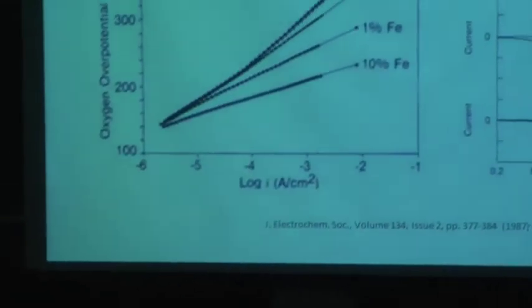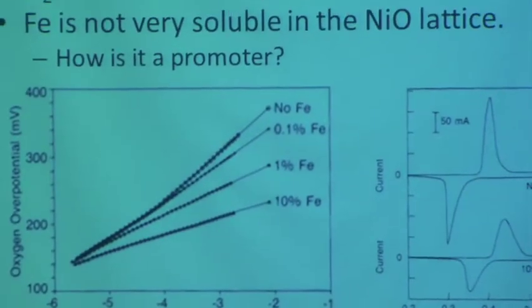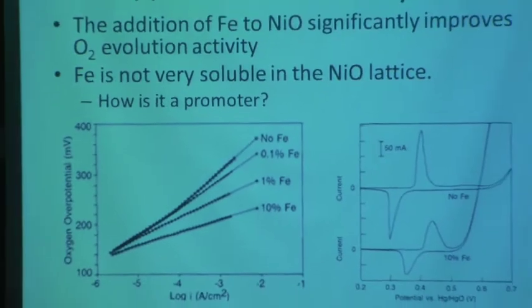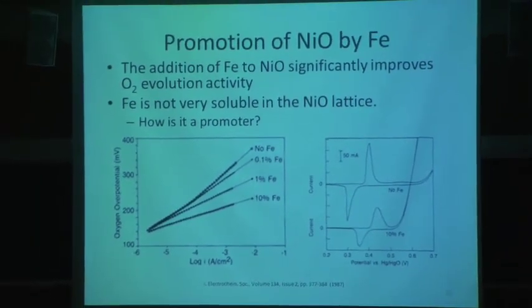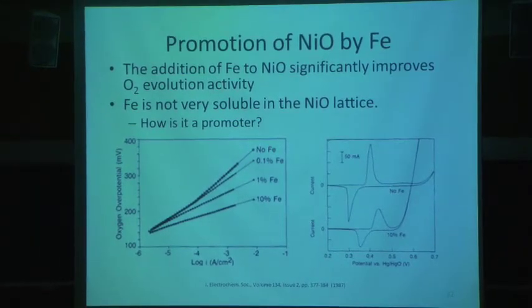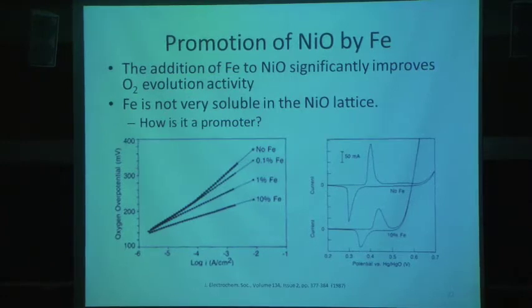All right, so I'm going to switch now to thinking about the experimental work in my group and trying to understand some of these promotion mechanisms. So it's actually been known for quite a long time. If you take nickel oxide and you add some iron to it, this iron can actually just be an impurity in the electrolyte, and if you cycle it, it gets incorporated into the nickel electrode, and you get a very large enhancement of the oxygen evolution activity.